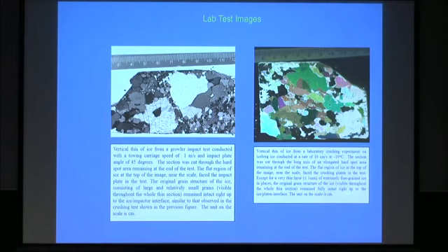Another one here. So this is the original iceberg ice. There's no change in the iceberg ice structure associated with these impacts. Those are the original grains with the air bubbles and so on in there. And you can see some remnants of this slurry layer that I was talking about. You see that up here, very, very fine grain material at the top.